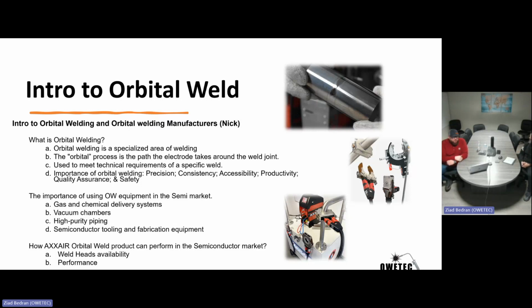And then as far as maximum, I'll speak from experience. I've welded with orbital welding, and this is per ASME. There's only a certain amount of maximum you can go to without adding filler material. But I've done 4-inch Schedule 40 pipe with orbital fusion welding on stainless steel 316L. Wow. Yeah, then you're going to do what we call a step mode.